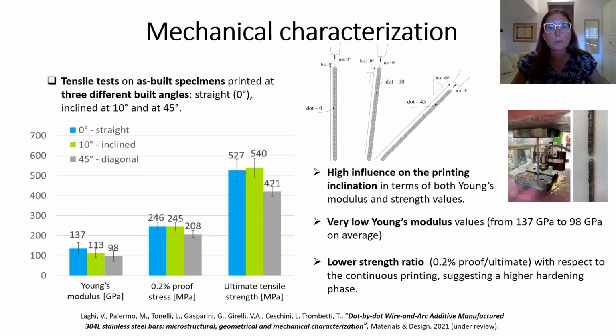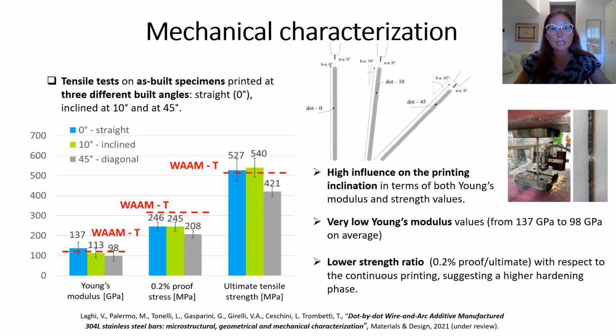The mechanical properties were derived through tensile tests on as-built specimens printed at 3 different build angles: at 0 degrees, at 10 degrees, and at 45 degrees. The results revealed a non-negligible influence of the printing inclination, with a detrimental effect especially for the specimens printed at 45 degrees. In comparison with the results of the continuously printed specimens cut along the T direction, so the transversal, which is perpendicular to the deposition layer, the Young's modulus values are on average the same, while the 0.2 proof stress, which is the yielding stress, is quite reduced for all inclinations.